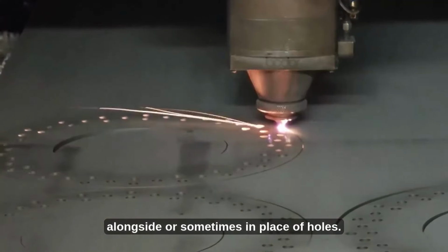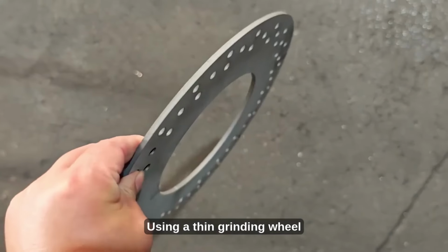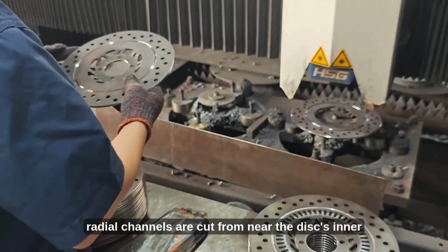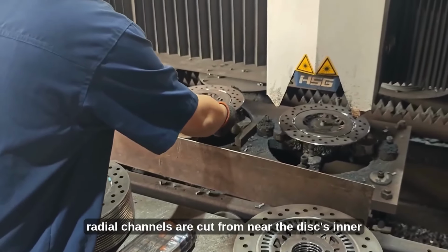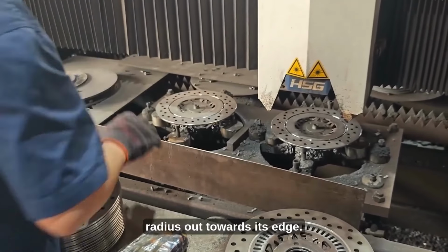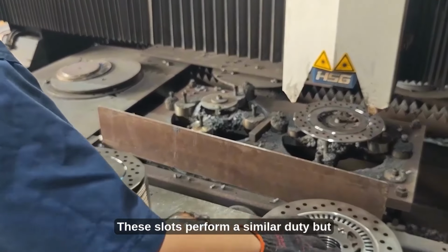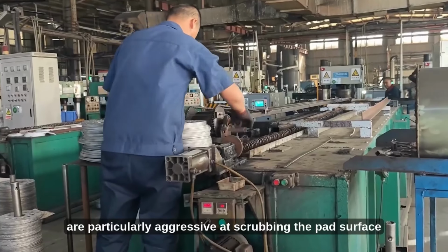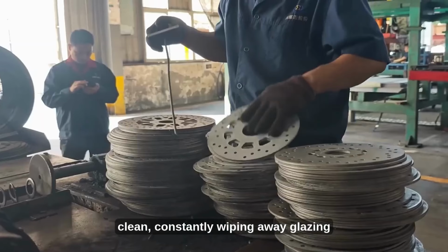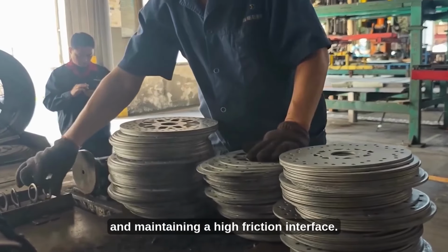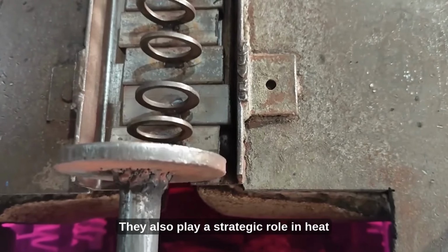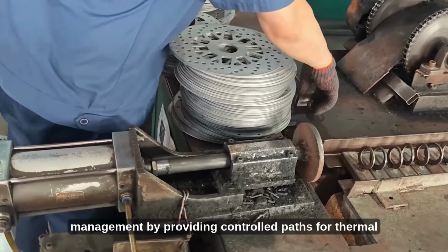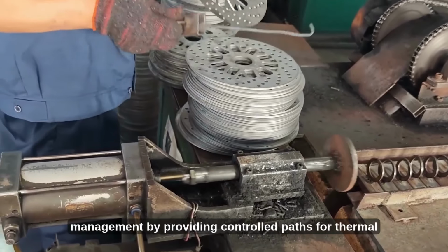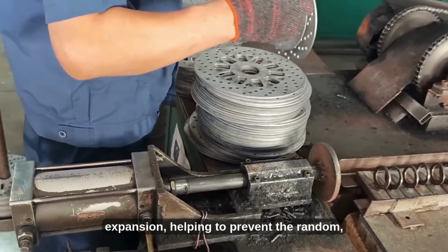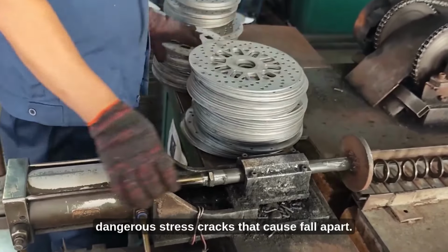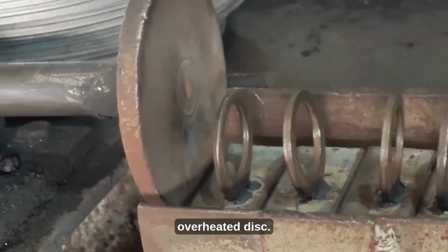Alongside, or sometimes in place of holes, come slots. Using a thin grinding wheel or slitting saw, radial channels are cut from near the disc's inner radius out towards its edge. These slots perform a similar duty, but are particularly aggressive at scrubbing the pad surface clean, constantly wiping away glazing and maintaining a high-friction interface. They also play a strategic role in heat management by providing controlled paths for thermal expansion, helping to prevent the random, dangerous stress cracks that can form in a solid, overheated disc.